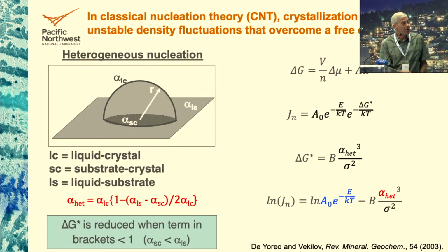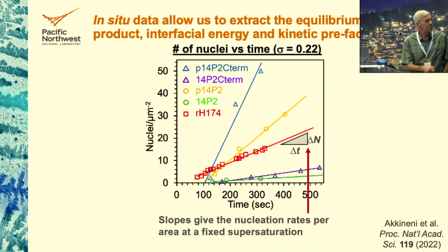So if we know what our supersaturation is, and we do this experiment as a function of supersaturation, we can measure the rates, we can get these numbers. And so that's what we did. So first of all, here's a plot of the number of nuclei per area versus time. The rate goes up for a while, and then it becomes 0 because you get the surface all covered. We only take the data from the region where the rate is increasing. And wherever it's increasing linearly, you know that you're in an area where nuclei are not affecting one another. They're all independent events. Now you can take the slope of this, and that gives you the rate, the number per area per time. You can see that this is for all 5 of these sequences.